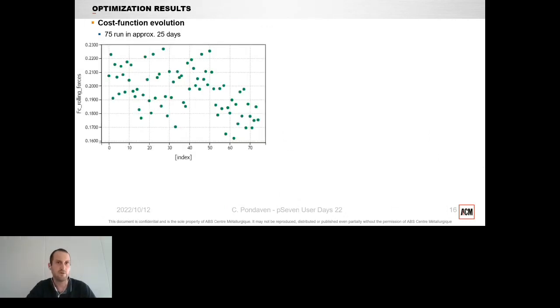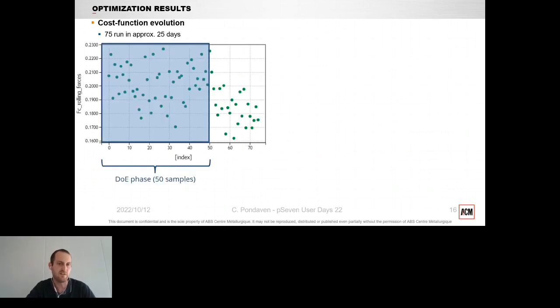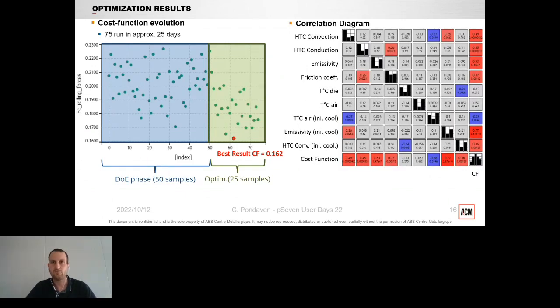So here is the result of the optimization procedure with the evolution of the cost function during the optimization phase. We can identify the DoE phase which uses 50 samples, and then the real optimization phase where the cost function is actually reduced to an optimum that we can see here. As a result, we can also compute automatically the correlation diagram that shows the contribution of each parameter to the cost function.